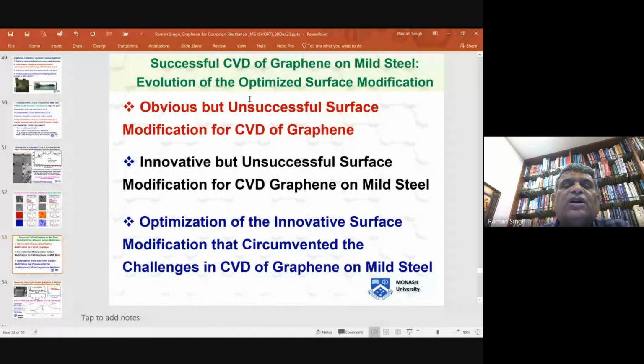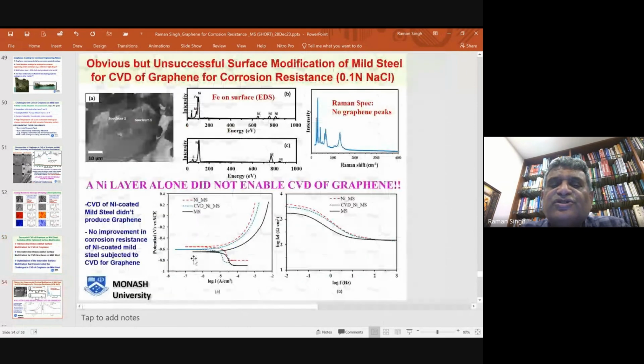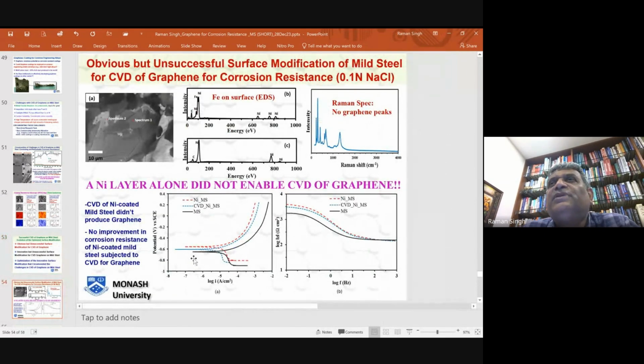does not work. We undertook obvious measure for surface modification, and that was unsuccessful. Then we undertook what we call innovative approach of surface modification, but it did not work until we optimized the condition, and then it worked. So I showed you earlier that it is easier to develop multi-layer graphene on nickel. So how about just putting a thin layer of nickel on mild steel, and then you develop graphene on nickel. Top surface is nickel. It does not work.